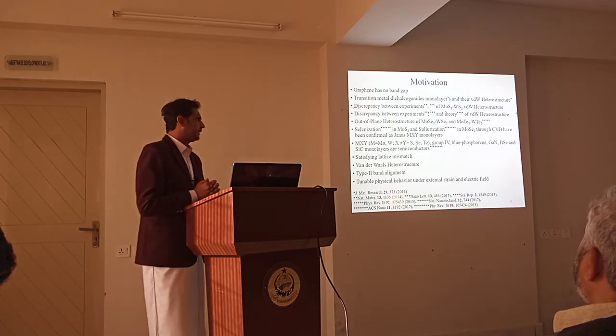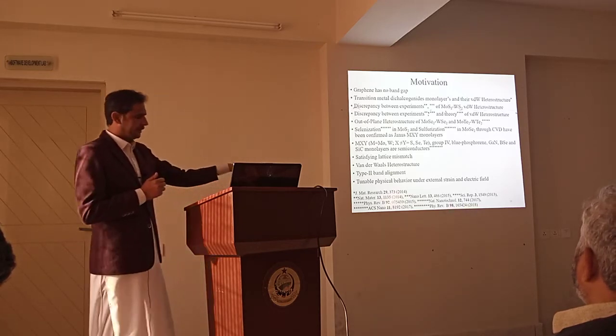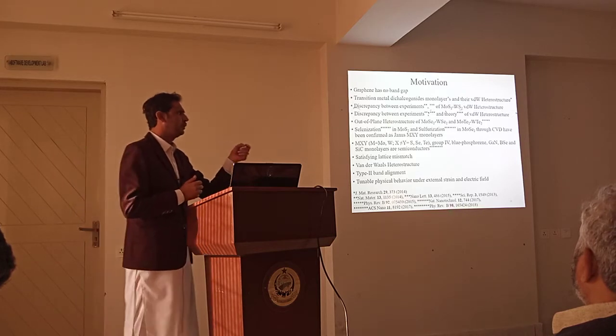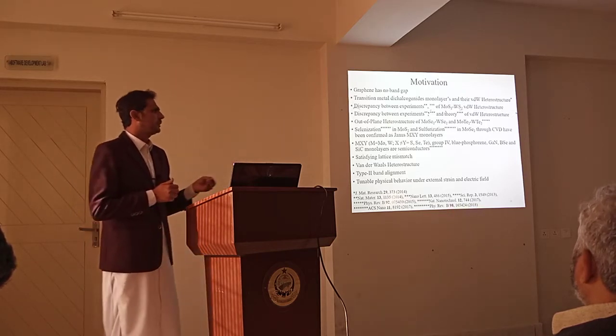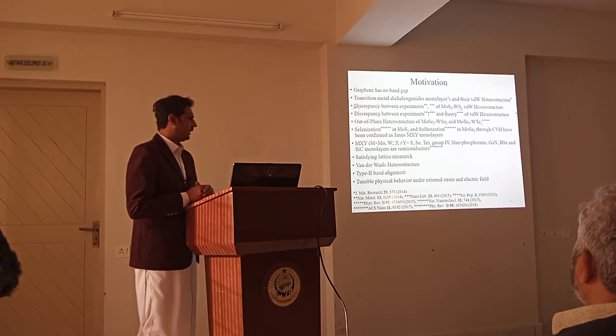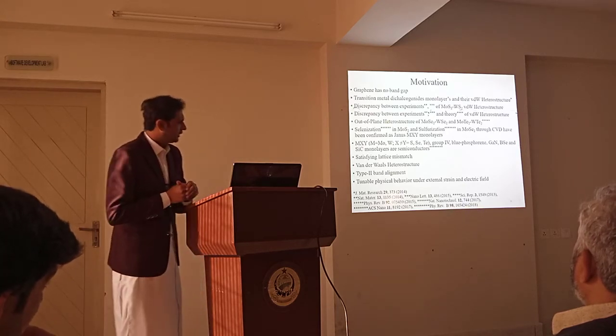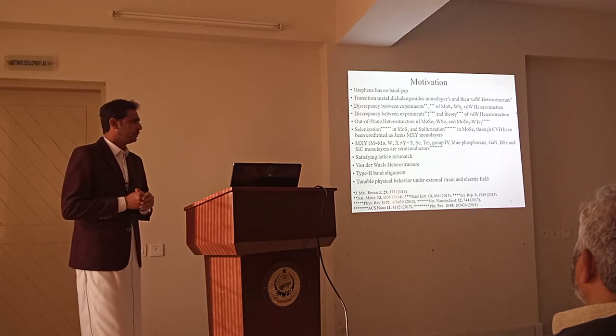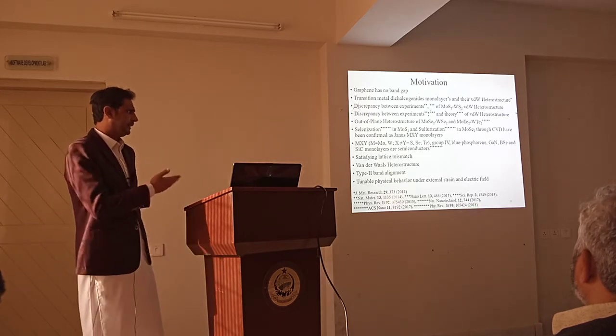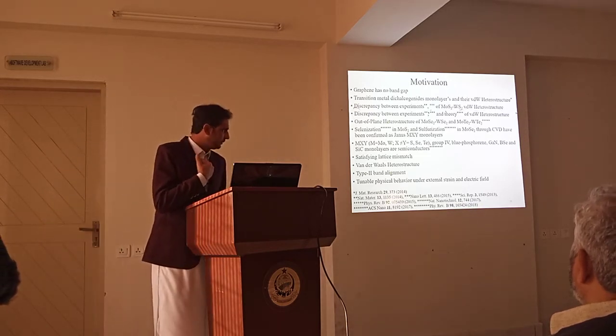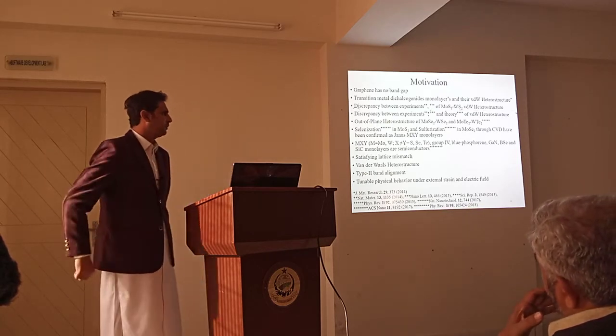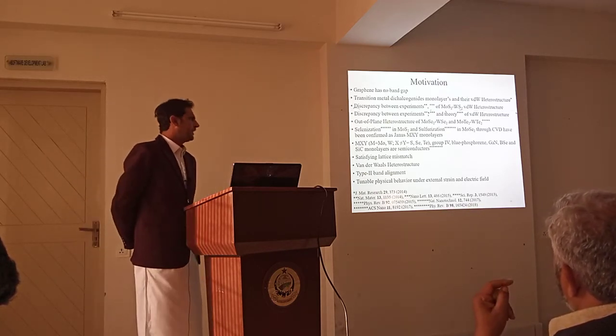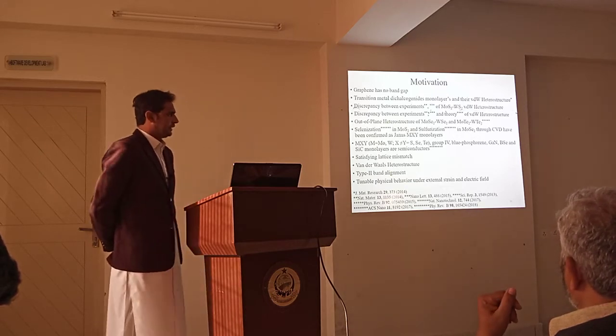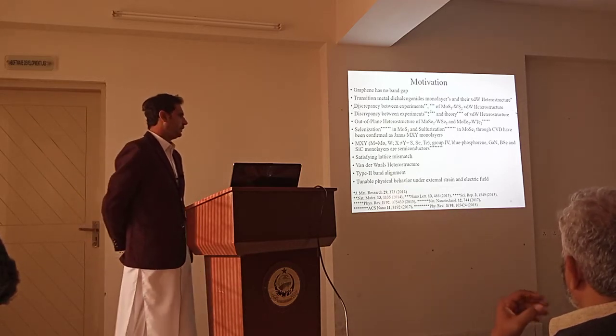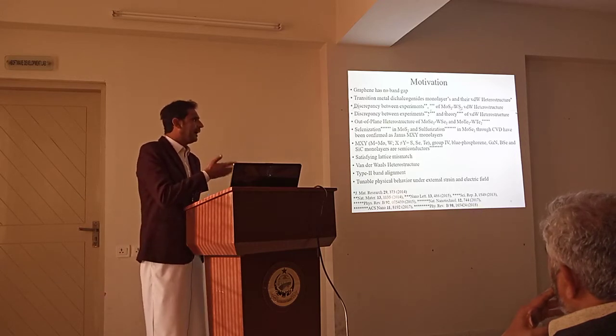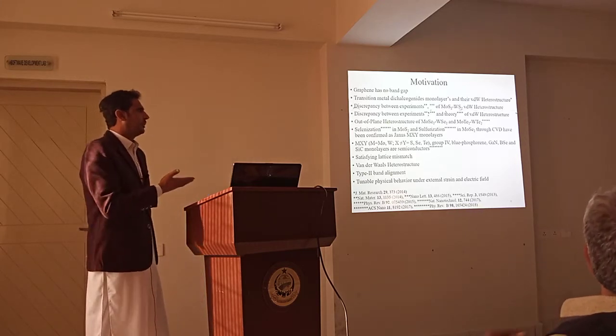The discrepancy between experiment, where I present references for MoS2 and WS2 van der Waals structures, and theory of van der Waals structure, out-of-plane heterostructures of MoSe2, WSe2, MoTe2 and WTe2. Selenization has confirmed the Janus monolayer by chemical vapor deposition process. MXY means Janus monolayer. Group 4, blue phosphorene, GaN, BAs and SiC monolayers are semiconductors. And all these monolayers mentioned here satisfy lattice mismatch.